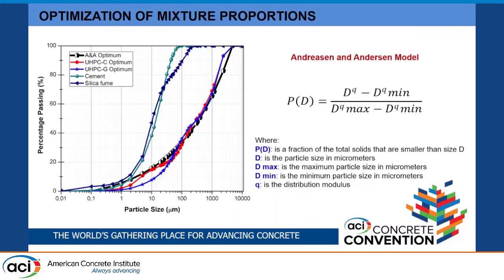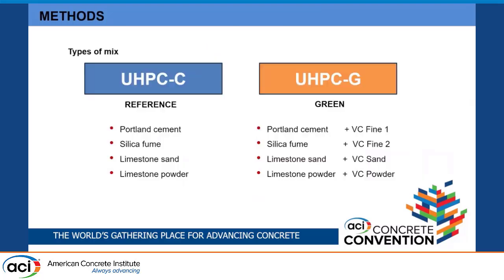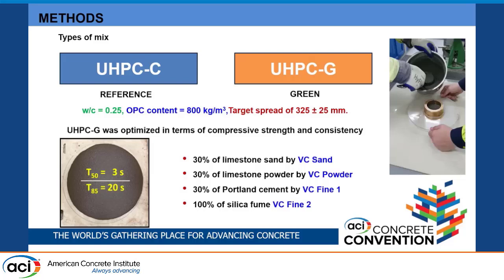And also another important step in the process is to ensure the maximum packing density of the particulate materials, and for this purpose we use the Andreasen and Andersen model. So with this model we define the combination of cement plus silica fume plus limestone sand plus limestone powder, and that leads us to obtain the maximum packing density. Okay, that's another important step.